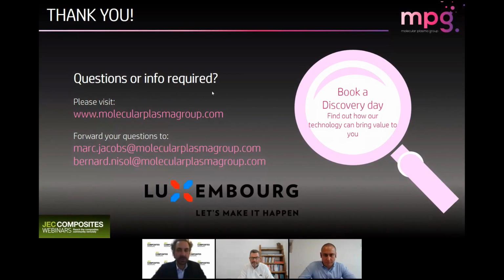When we were talking about your production platform, can you give an indication of typical line speeds? The system you saw for the non-woven material will be running at about 30 meters a minute, which then translates into the number that was on the screen of 5,000 square meters per shift. It's a bit chemistry dependent, function dependent. You can imagine if a 10 nanometer layer does the job, it's going to run faster than a 50 nanometer layer.